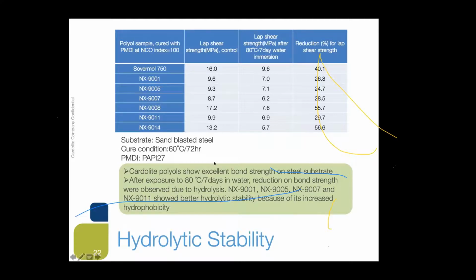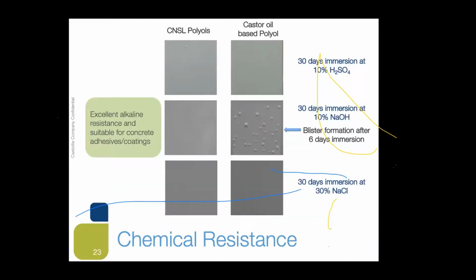We check mostly on the 80-degree for 7 days immersion test, particularly for this polyol. And as I mentioned, this polyol, slide number 23, these polyols have a better alkali resistance compared to castor-based polyol. This is another advantage in the CNSL. If you look at this slide, CNSL, we compare and generate data in our lab.